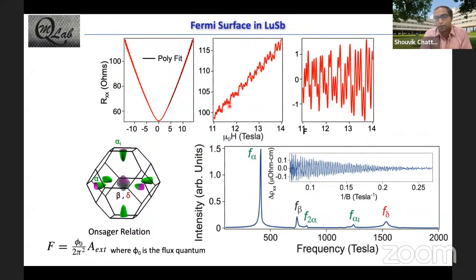And here I'm showing you Shubnikov-de Haas oscillations from where we can extract the different frequencies just by doing a fast Fourier transform. And from there, by using this Onsager relation, we can get an idea about the different wave vectors of the Fermi surfaces in this material system. This is just to orient what you would expect for lutetium antimony, for example.